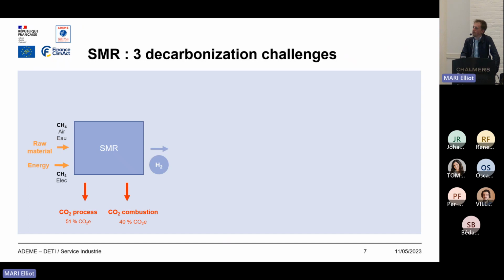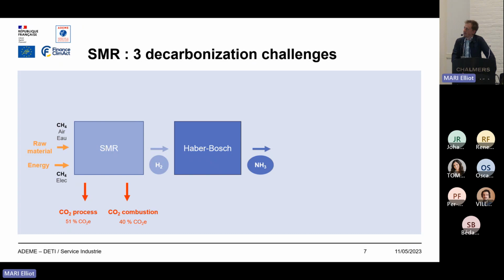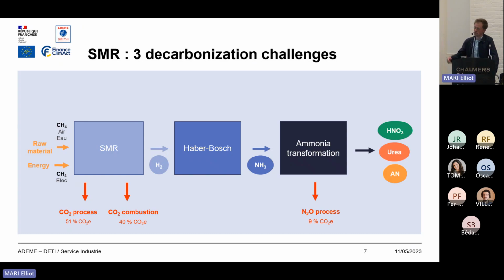So just before talking about pathways, I would like to remind you of the decarbonization challenge of the production of ammonia. The production of ammonia is based on steam methane reforming. So you have natural gas, air and water as raw materials, and natural gas also as an energy provider. The steam methane reformer is here to produce hydrogen. Then hydrogen is transformed into ammonia through the Haber-Bosch process. And the ammonia is again transformed into nitric acid, urea, or ammonium nitrate. Here you can see the GHG emissions, which are heavily located on the steam methane reformer, but also on the ammonia transformation into nitric acid because of the nitrous oxide emissions.